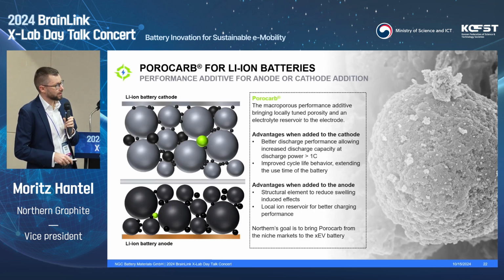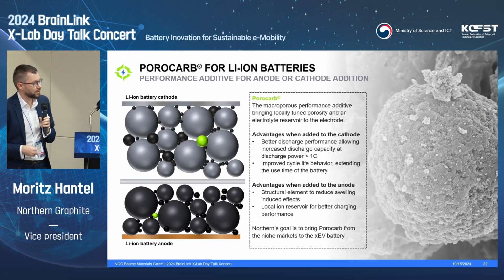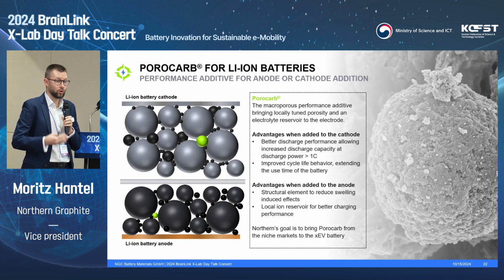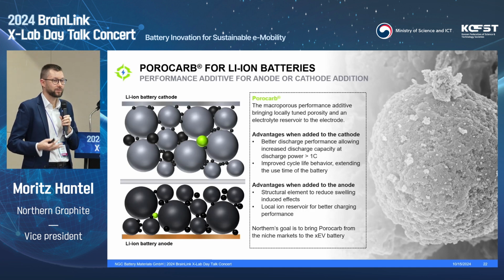And looking at the advantages you get out of the system, we see a better rate capability in terms of power. So going to higher C rates, so higher discharging powers, we see that we can recover more of the stored energy. At the same time, it improves the cycle life performance, since having a more homogeneous electrolyte reservoir and electrolyte availability helps over the lifetime of the system.